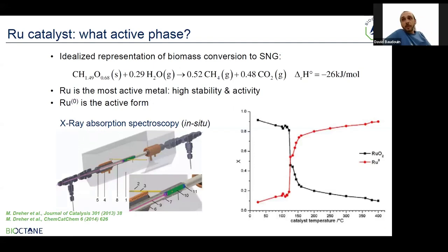And the big question is, what is the active phase in this catalyst? When we start, ruthenium is exposed to, of course, reductive conditions, but there's a large excess of water. So for a long time, the active phase was believed to be ruthenium oxide. It turned out, by doing an in situ X-ray absorption spectroscopy study, you can see on the right, that there is direct proof that the ruthenium gets reduced very easily, as early as 150 degrees C. It gets reduced to ruthenium 0. So this was direct proof that ruthenium 0 is actually the active phase under these conditions. Next slide, please.